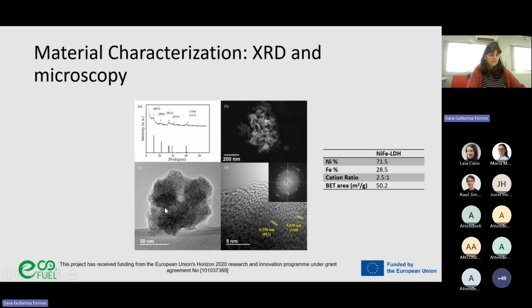Here at the bottom, the TEM image shows that the particles are composed of the aggregation of nanosheets in the range of tens of nanometers. And here on the right, the high-resolution TEM image shows the typical spacing for LDH structures that can be assigned to some of the crystallographic planes that were already observed in the X-ray diffraction pattern.